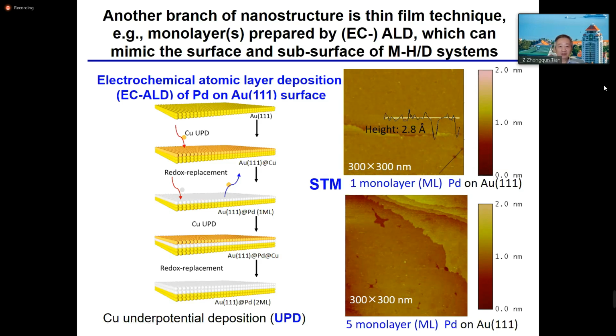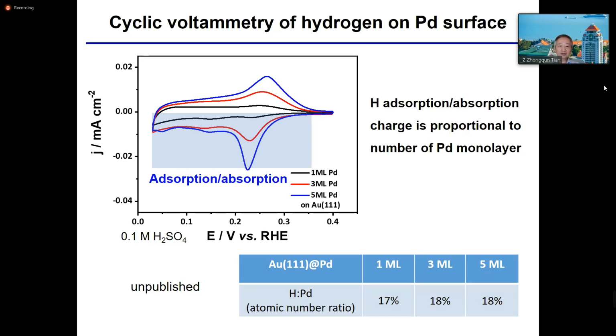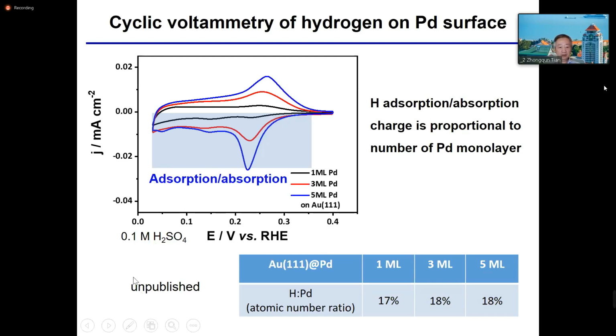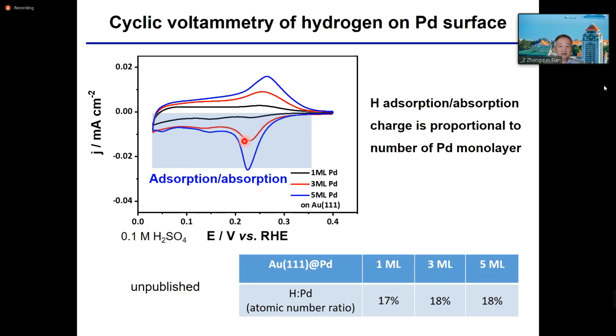So I've been working with Jianfeng Li for many years. As you can see here, we utilize electrochemical cyclic voltammograms of hydrogen. You can see this is the first layer of palladium. And then we have the third layer here, then five monolayers here. So as you can see, it increases the thickness and increases the underpotential deposition of hydrogen.